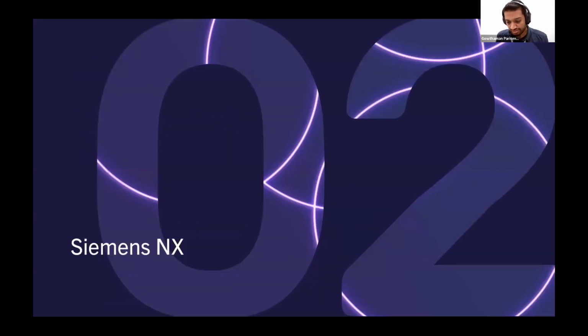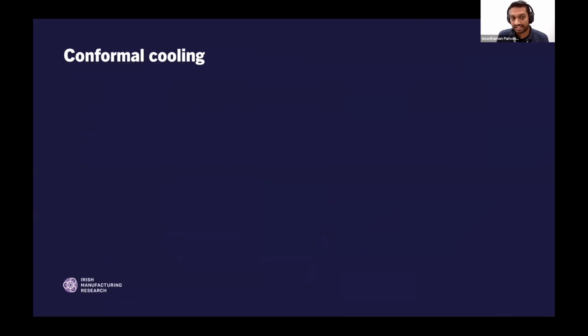In the next session, I will walk you through the workflow that we implemented in a project where numerical simulations played a crucial role in enhancing the process. Conformal cooling is a mold cooling technique in which we ensure a uniform temperature gradient through the cooling process. So why do we need this? In injection molding, when the part is cooled by the cooling channels, non-uniform cooling builds residual stresses in the part. When the part is ejected from the mold, it might deform. This, of course, is not desirable for the company. Also, because the cooling channels put in effort in cooling the bulk of material as well, there's increased cycle time.